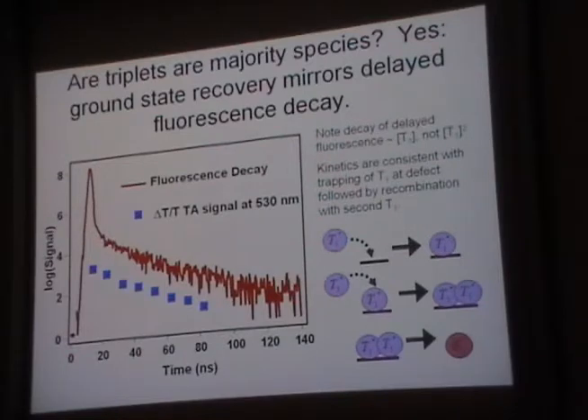Okay? So if we make the assumption, which I think is very safe, that the delayed fluorescence is due to triplets, and then we say, well, is there anything else? Well, if there is, the bleach should be different, but it's not different. It's the same recovery time as the decay of the delayed fluorescence. And if you have a different sample or a different intensity and you change this decay rate, this decay rate changes as well by the same way. So it doesn't look like there's something else.